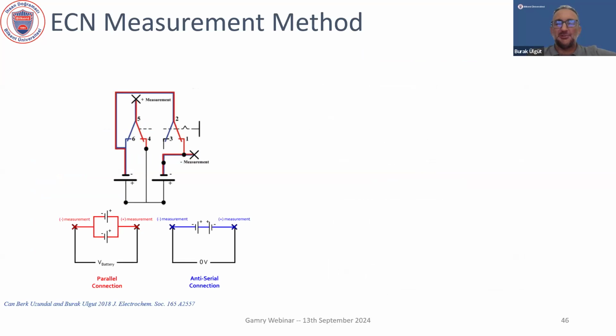My first noise paper shows exactly the electrochemical noise of supercapacitors at different voltages, showing the effect of electronic noise of the voltage reference. So in order to compensate this voltage, we are using another battery to compensate the first battery. So we keep them in parallel connection for a while so that they equilibrate to the same point down to the microvolt. And then we very quickly switch them to what we call anti-serial, which is a serial connection, but the poles are back to back. So the positives are facing each other. And this way, the DC potential between negative measurement and positive measurement is 0. And that way we can measure the voltage directly.